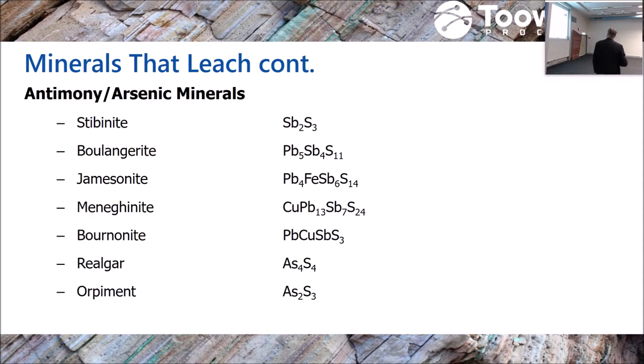It works on antimony systems. The only difference between arsenic leaching and antimony leaching, and there was a large body of knowledge around antimony leaching 30, 40 years ago, Corby Anderson, the Equity Silver plant, and a number of plants, is that antimony leaching needs a lot more sulfide to complex in the leach solution. The arsenic needs more oxygen. So in discovering the chemistry in the Toowong process, it was really about understanding that arsenic is different to antimony, and it needs a higher oxygenated environment, not as in oxidative, but the hydroxyl ions.